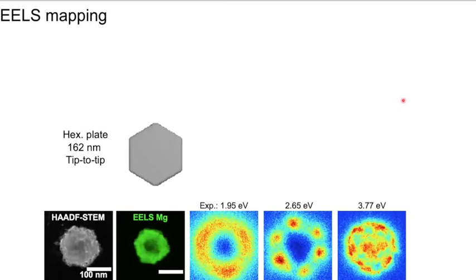All right, so we get this map. We extract basically the probability of excitation at specific energies, and we get these kinds of things. Okay, so here's the particle, what it looks like. Here's where the magnesium metal is. It looks roughly hexagonal, and there you have three modes. The first mode looks kind of like a donut. The second mode looks like it has field intensity, or loss probability rather, at the tips of the particle. And the third mode looks like maybe field intensity at the edge and the center of the particle. And if you're an experimentalist like me, you just end there and you call this mode the donut mode for the rest of your life without really understanding.